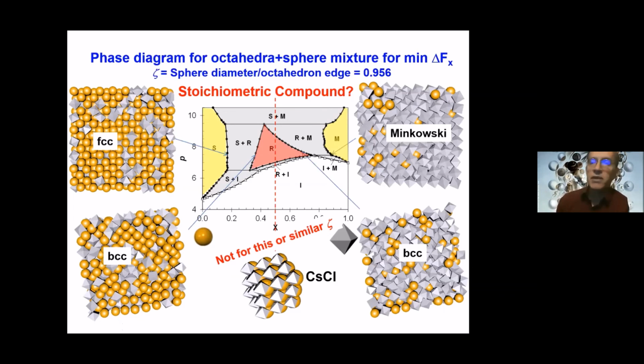Now, sometimes you have these phase reversals, where what is supposed to be isotropic became Minkowski, or what was supposed to be Minkowski became isotropic. But you analyze it through order parameters, just to see, is there any orientational order? Is there any positional order? And we found that it was forming this phase over there. Now, okay, so some order parameters.